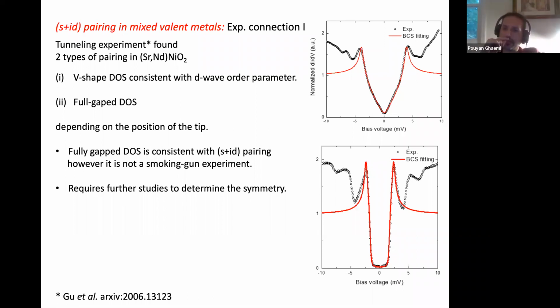Also, are these samples a single crystal or multi-crystal? They are thin films, and they are definitely very dirty. It's very, very challenging to make clean samples of these, mainly because this hydrogen reduction process really creates a lot of disorder. That's one of the reasons why there's experimental controversy on reproducibility. All right, so this is the first connection with experiments. Again, we cannot really say, but it is actually quite encouraging.